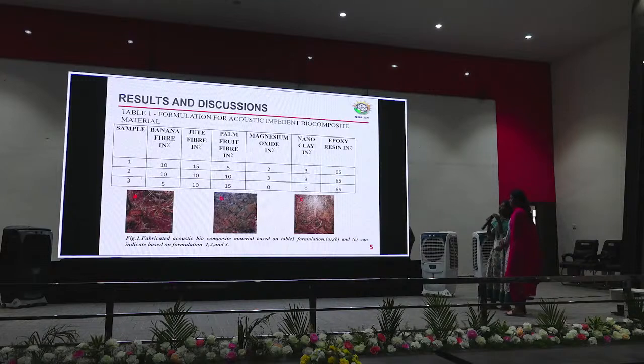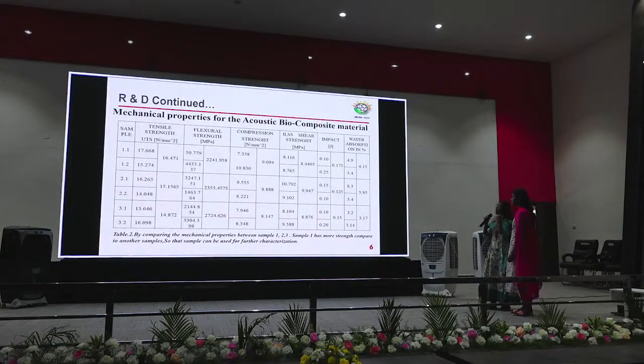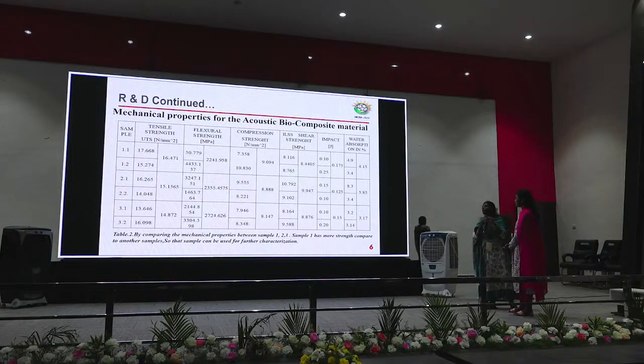Next. Here we show the fabricated material, which we formulated in three different formulations. A shows formulation 1, B shows formulation 2, C shows formulation 3. Next. First we analyze the mechanical properties based on 6 different mechanical characterization variables. For each sample we take 2 sample pieces, labeled 1.1, 1.2, 2.1, 2.2, 3.1, 3.2. By comparing the averages, sample 1 shows better mechanical properties, so it is used for further characterization. Next.